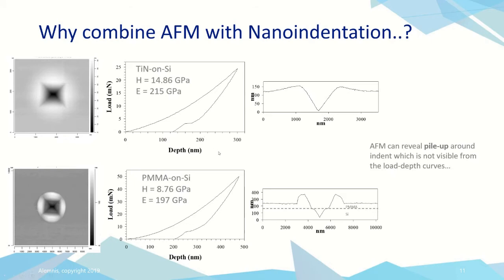But what is interesting is that we see very nicely the pileup around the indent in the case of titanium nitride, but it's different to the case of a soft polymer where the material is simply pushed out to the sides. So AFM tells us exactly what's going on and what the response of the material is.